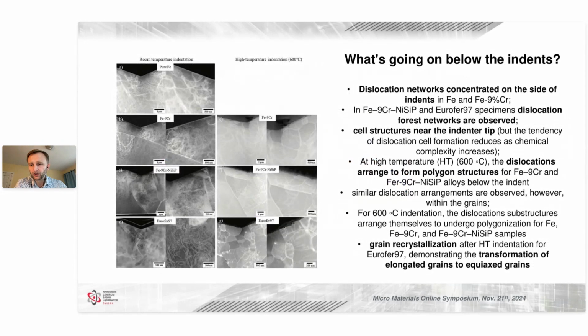So in the next step, we did detailed transmission electron microscopy analysis below the indents. And I apologize for the amount of text, but what I want to say is that depending on whether indents were measured at room temperature or at high temperature, we observed different structures. At room temperature, dislocation networks appear on the sides of the indents in the case of iron and iron 9% chromium, or we see dislocation forest networks in the case of the two more complicated alloys. When we go to high temperature, we see that dislocations arrange to form polygon structures in model materials, whereas in the commercial Eurofer 97, there is grain recrystallization and transformation of elongated grains to equiaxed grains.